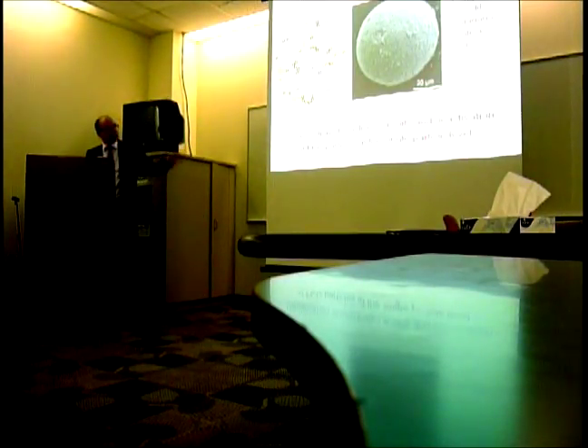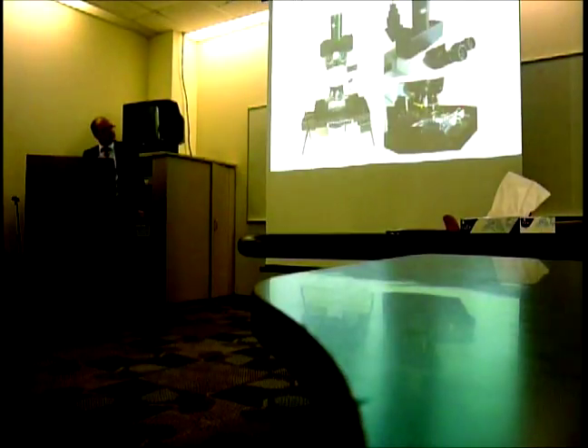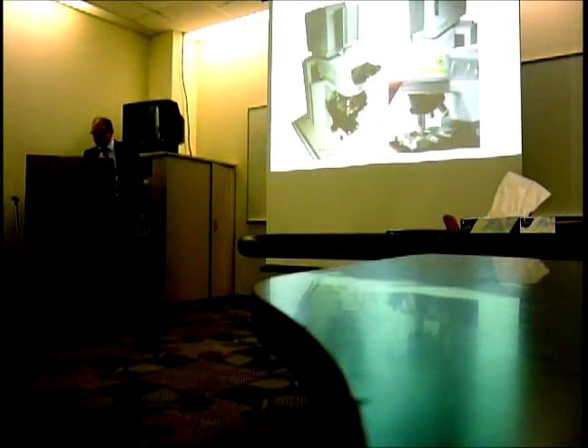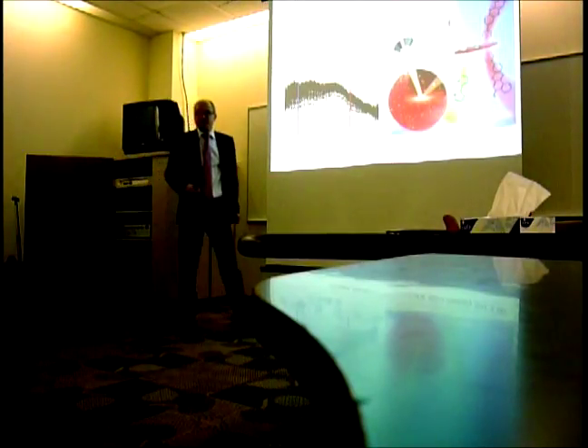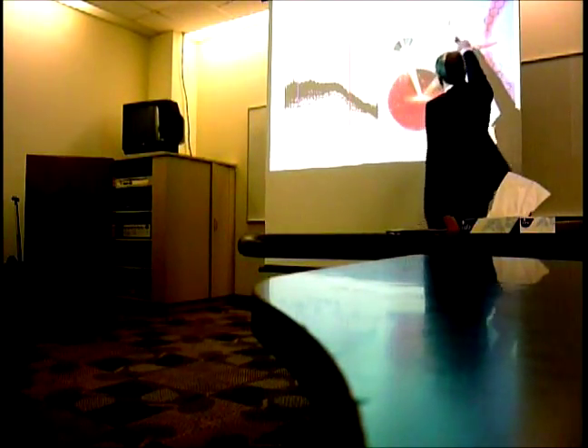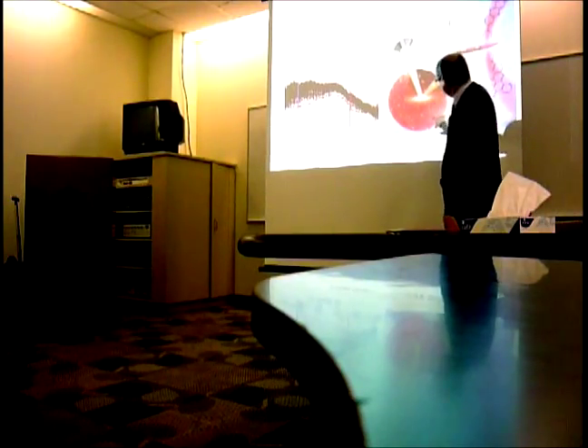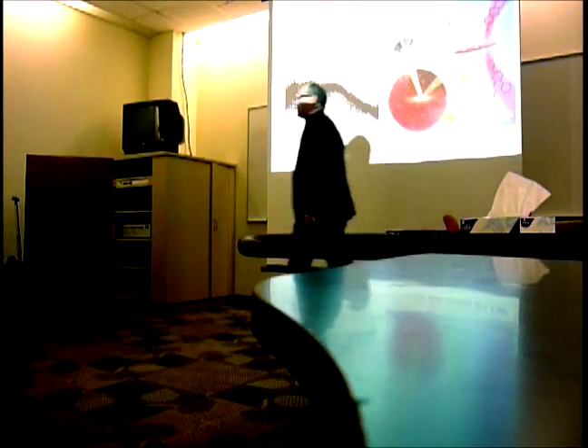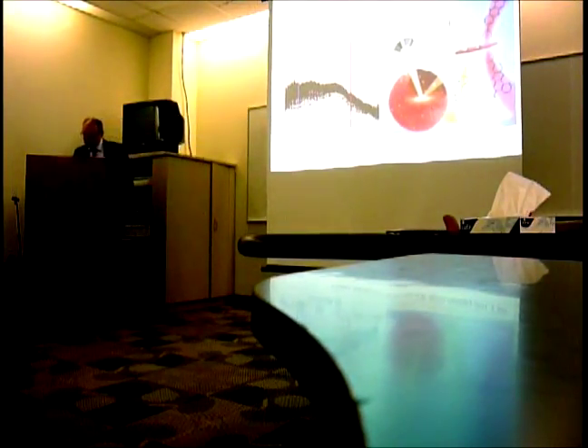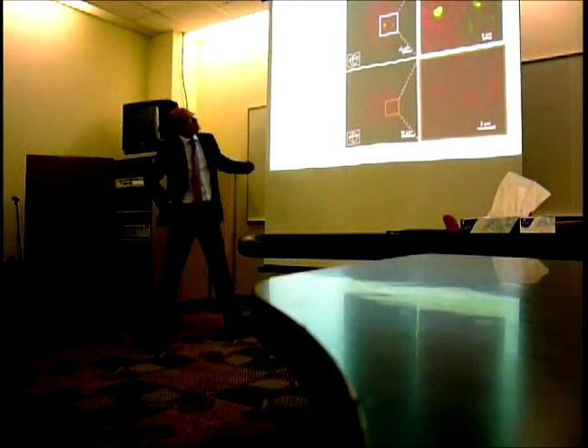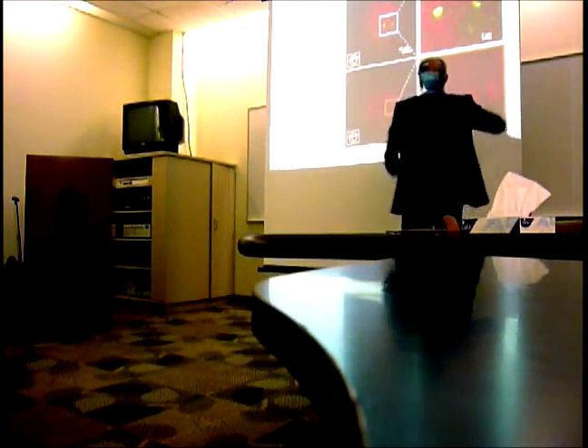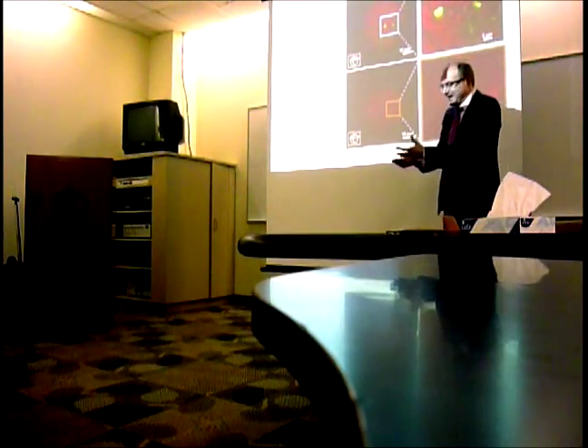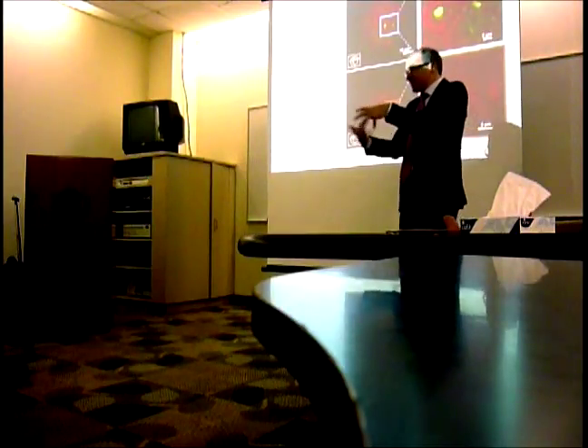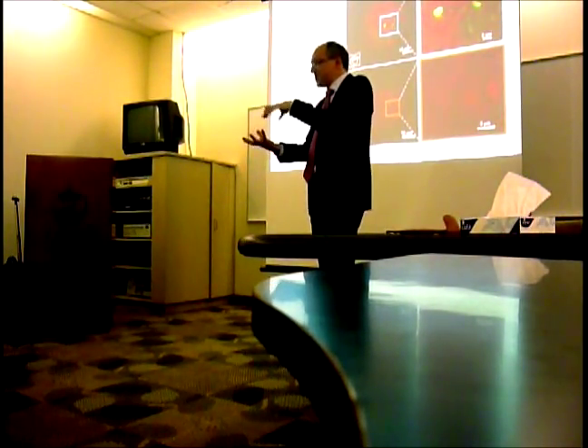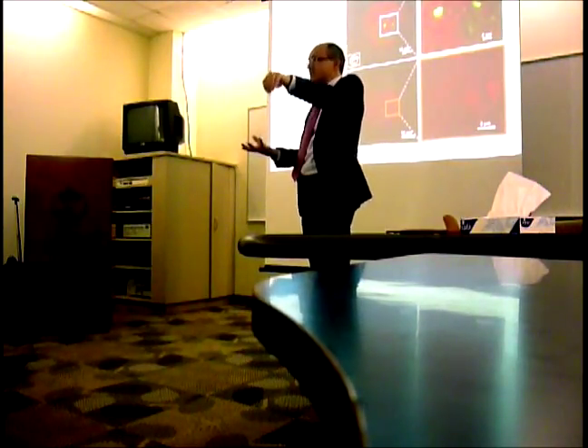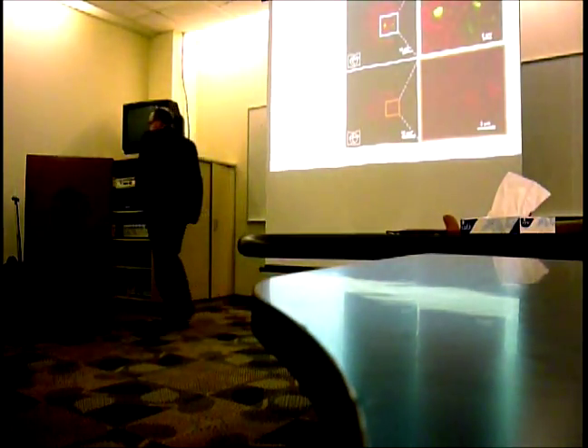Question. We use the staining reaction, I will not dwell in detail on it. We can do UV-vis microscopy, we can do certain characterization, and now I come to the real experiment. We use the reaction in which thiophene is oligomerized, giving rise to these green dots. And now I will show you that we indeed can make this visual. So here on top, I show you the ball, and the green spots are the zeolites. So you can really selectively, as with a cell, localize in 3 dimensions where the zeolite, the active component, is within this material.